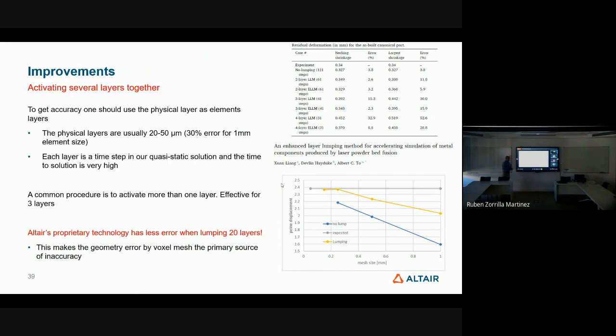Then we took it in another way. We checked that we can do something quite interesting in the element itself, and finally we came up with our own way of lumping. As you can see here, this was for a 0.02 layer thickness. With 10 layers you get the exact result, in fact also with 20 layers. With 30 layers, you get about 10% error. So that was an important push for the performance of the solver. This means that we can go 10 times faster or 30 times faster, and this is an important leap to the market.